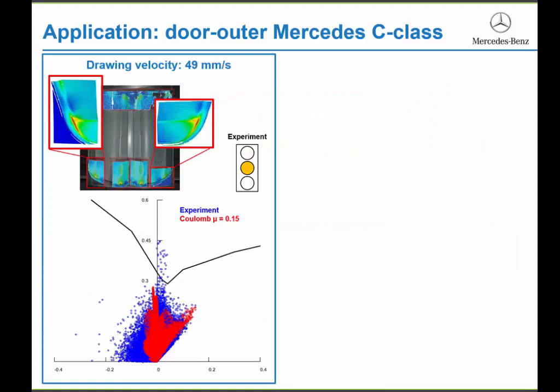So if we look at the tryout production, we see the part in this figure. We also see the areas where strain measurements have been performed. If you look at the 2 corners, so at the left bottom side and the right bottom side, these are the corners where, if cracks occur, you would expect them in these regions, so in this corner.